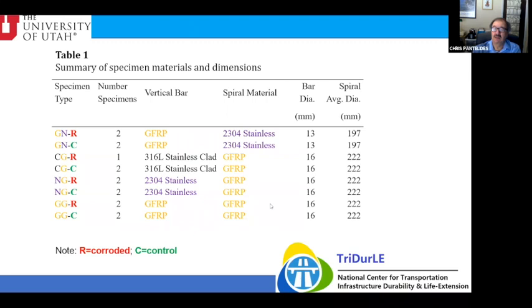So I mentioned earlier that the bar diameter was a little bit different. For the vertical GFRP, we used 13 millimeter, and all the rest was 16. And for the spiral, that meant that the diameter would be a little bit bigger. We use 16 because with the fiberglass spiral, the modulus is very low, about 1/5 that of steel. So we know we need a bigger diameter of the spirals to get the same confining pressure. Stainless, of course, is just a 1/2 inch diameter.